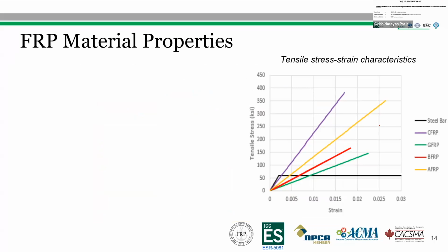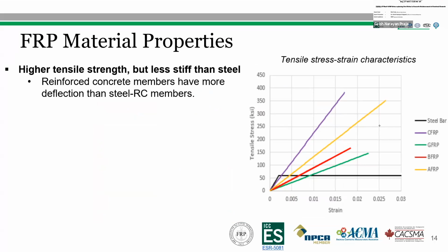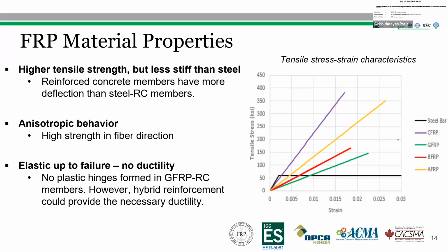This figure shows a stress-strain profile of the GFRP bar, and we can see here that the GFRP bar has higher tensile strength than the steel bar, but it is less stiff than the steel bar. Therefore, FRP reinforced concrete members can have more deflection compared to steel reinforced concrete members. FRP bars have high strength in the fiber direction due to the anisotropic behavior. The stress-strain behavior of FRP bars is linearly elastic up to failure, so they don't provide any ductility. However, this can be overcome by providing hybrid reinforcement of steel and fiber reinforced polymer bar. Current research is going on to implement hybrid reinforcement in the new ACI 440 design code.